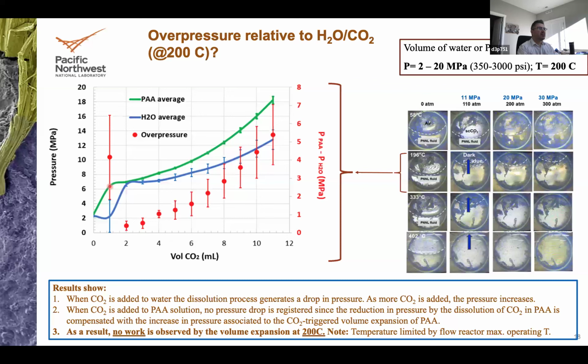So what happened here? Yes, there may be a volume expansion, about 30% at 200 Celsius. But the volume expansion compensates for any pressure drop associated to the dissolution. There is enough volume expansion that it does additional work up to 6 megapascal, the original pressure at which CO2 was added. So yes, there is an overpressure relative to water CO2, but there is no work in that cell associated to the expansion. It's just compensation for the pressure drop associated to dissolution of CO2.